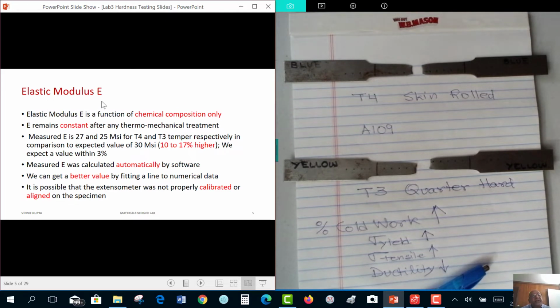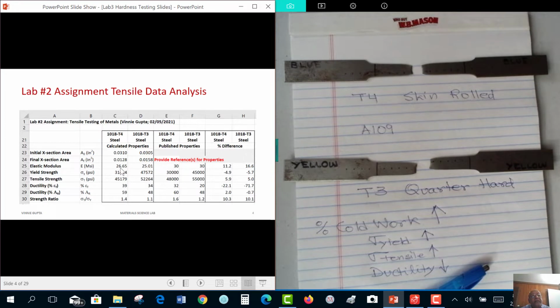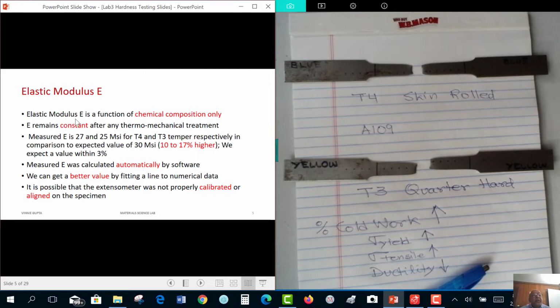So elastic modulus E, you saw first of all that we had values like 27 and 25 against the published value of 30. It's almost 10 to 15% off. Now, it turns out that elastic modulus E for metals is a function of chemical composition only. So if you are not changing the chemical composition of the material, you cannot change the elastic modulus. It remains constant after any thermomechanical treatment. So that means if we begin with whatever condition the steel is, we anneal it, we skin roll it, we make it quarter hard, we don't change its elastic modulus. It should remain 30 million psi.